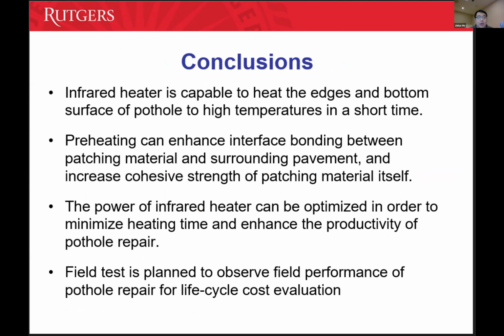So, a quick conclusion: the infrared heater is capable of heating the edge and the bottom surface of the pothole to a high temperature in a relatively short time, in a few minutes scale. This preheating will enhance the bonding between the patching and the existing pavement, and also increase the cohesive strength of the material itself, which is pretty good. And then we will be able to optimize the power to minimize the heating time and enhance the productivity of the pothole repair, because usually they only spend a few minutes per pothole in the field.